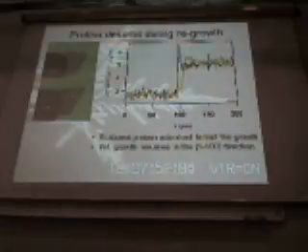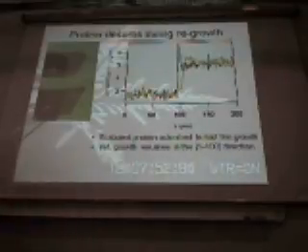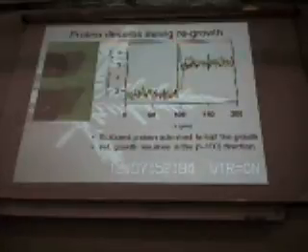So it means when the regrowth occurs, adsorbed protein reversibly desorbed from the interface and diffuses in the solution.